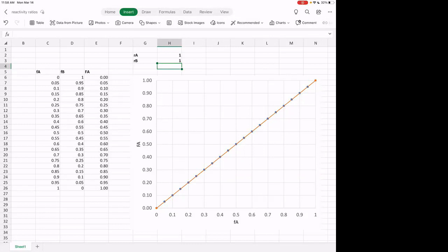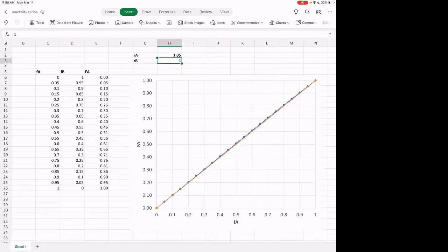Yes? In industry, are there actually true random polymerizations, or are they essentially random? They're very close. There's some reactivity ratios that are like 1.04 and 1.01 or something like that. Or there's 0.99, 1.05. So it's the real world. It's never perfect, but it's pretty close. So there'll be minimal compositional drift. If you look at this and let's put in 1.05, that line is pretty much on the 45, right? So you're going to get a teeny little compositional drift, but not a lot. So yeah, it's worth studying.